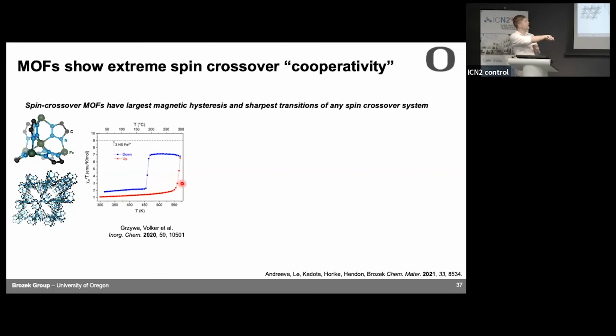And so you heat it, it will abruptly go into the high spin state. It'll stay in the high spin state. And then all of a sudden, it'll drop to the low spin state. This is called the hysteresis window. This is one of the largest hysteresis windows of any spin crossover system, molecular or material. Some argue it's the largest. These are also some of the most abrupt transitions.